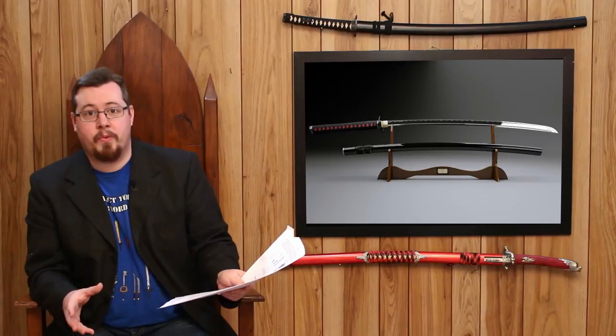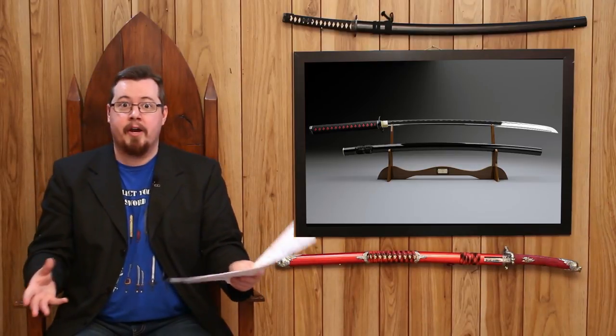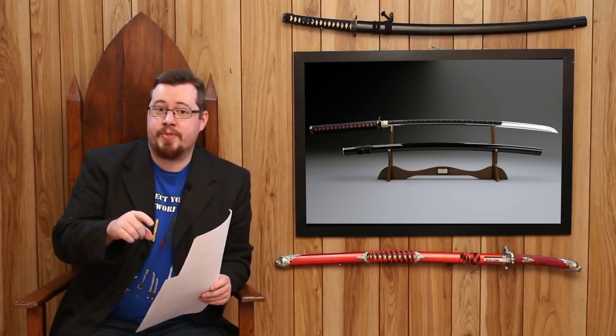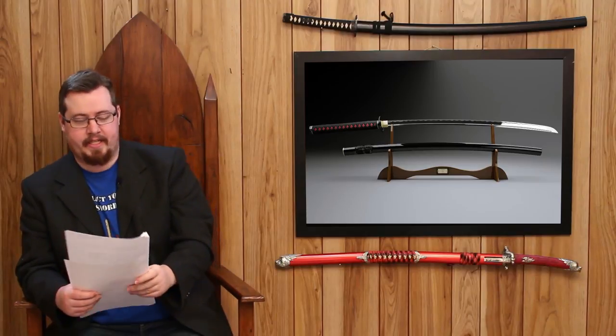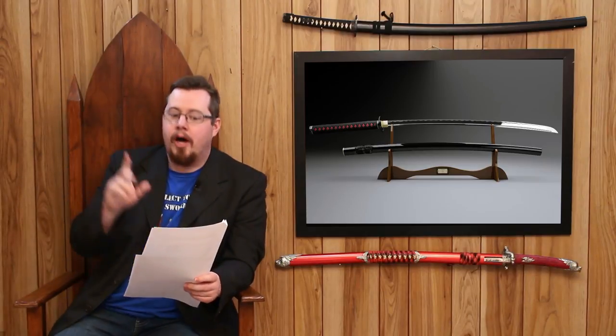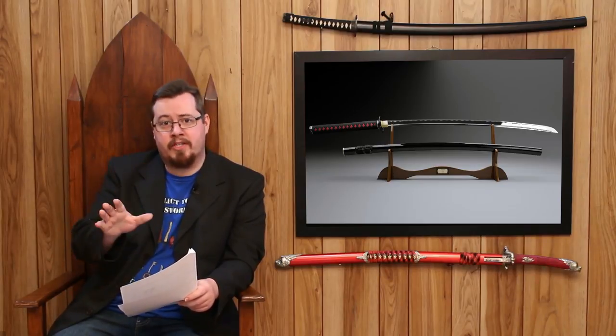Not nearly as much as what would happen if they didn't forge it, okay? Because remember, without forging, nearly all the slag content is still in there from the Tatara smelting process. And indeed, the parts of the sword that were forged more had fewer inclusions. It still had inclusions, but fewer, because the more you forge, the more you can get rid of. But look at the inclusions that were left, the non-metallic inclusions specifically. I'll mention them again: silicon dioxide, iron dioxide, titanium dioxide, and aluminium dioxide. Each one of them was an oxide, all right?